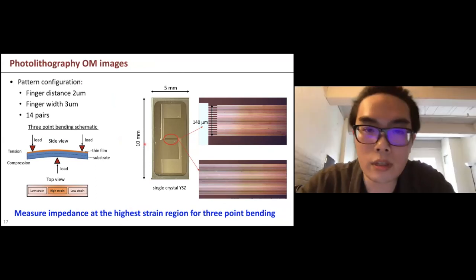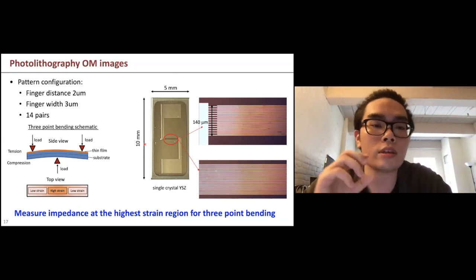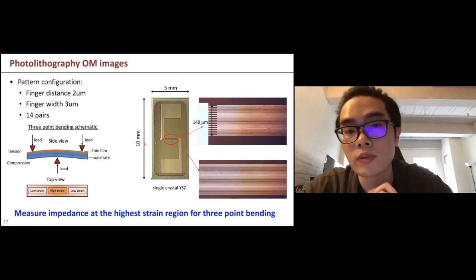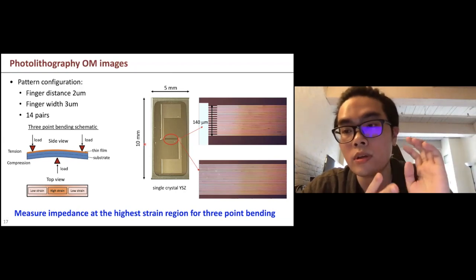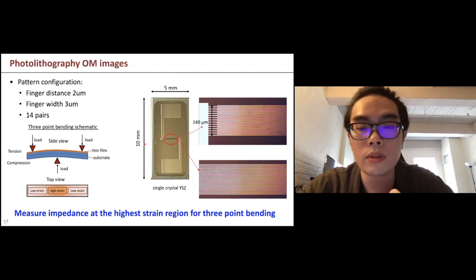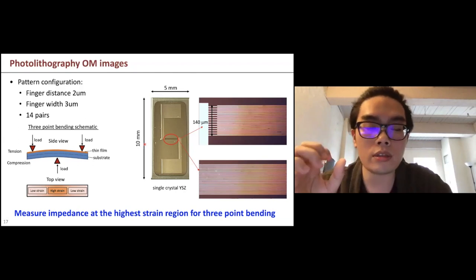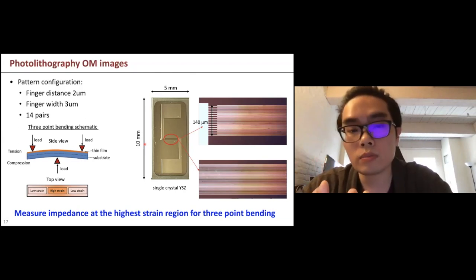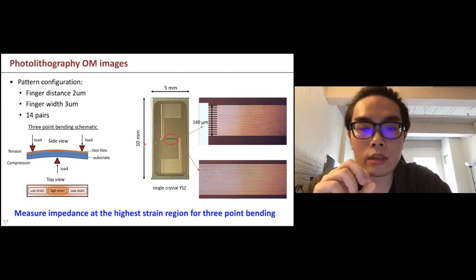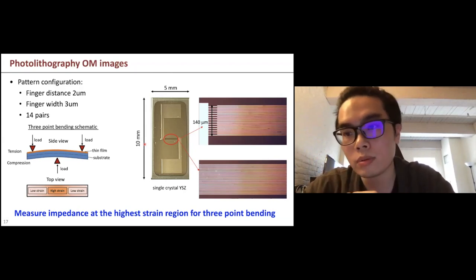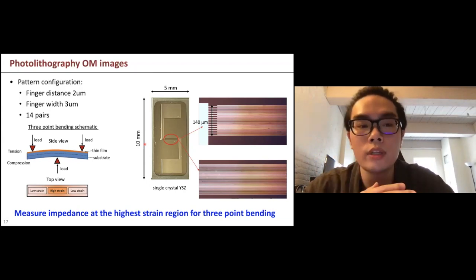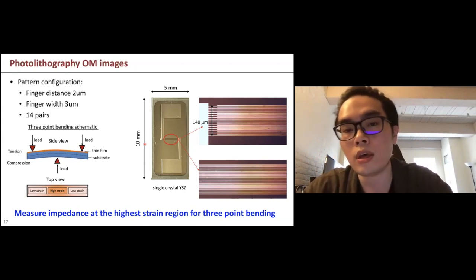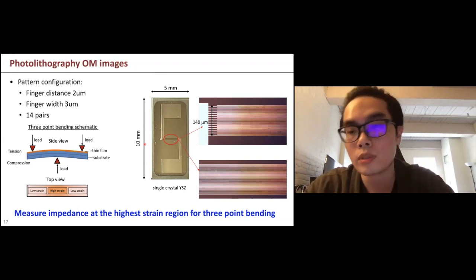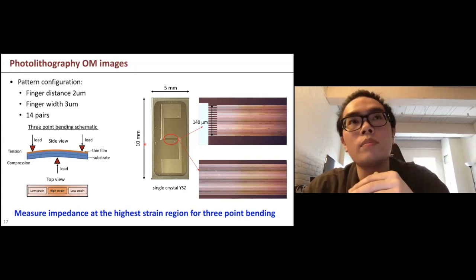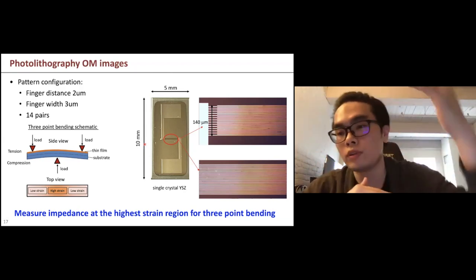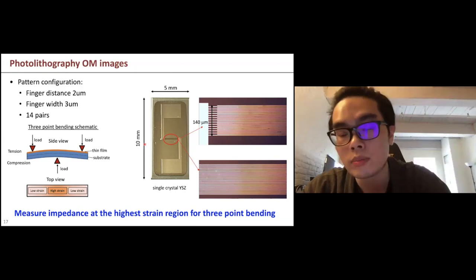So if I understand the question correctly, basically it is thinking about, because thin film substrates are different materials, they might have different thermal expansion coefficients. So when we raise the temperature, the sample might just have some pre-strain. That's actually why we use one sample, because at the same temperature, even if it is pre-strained because of the thermal expansion, when we apply the strain, they will have the same starting point. And how about a different temperature? They will have a different kind of pre-strain because of the different temperature.